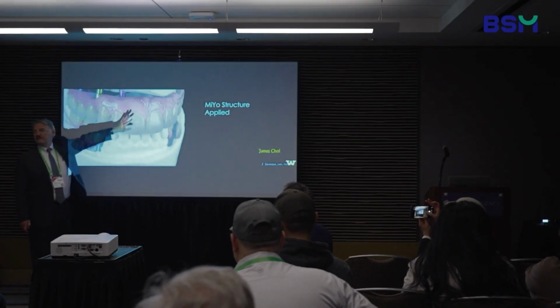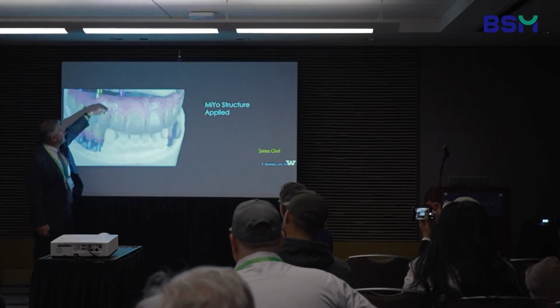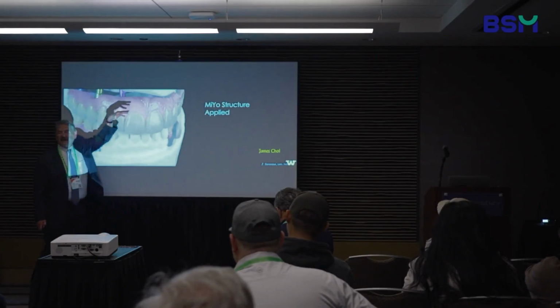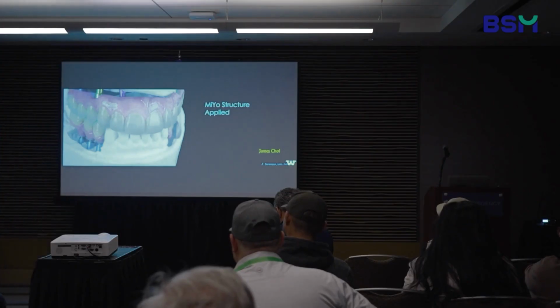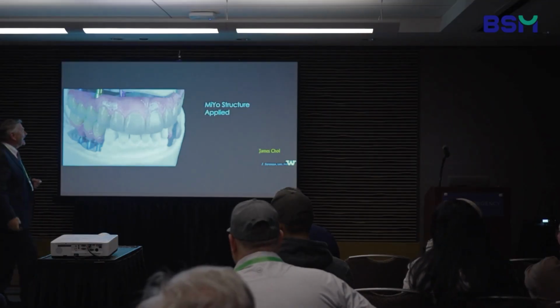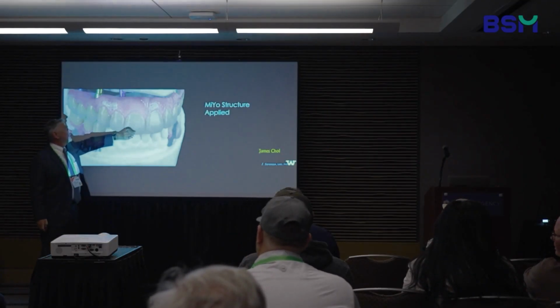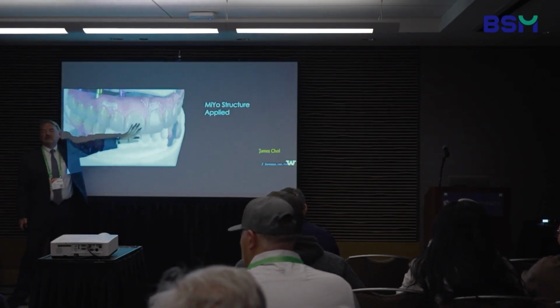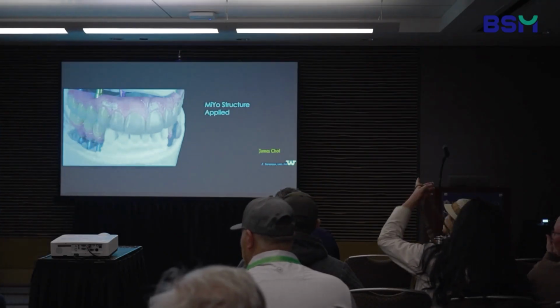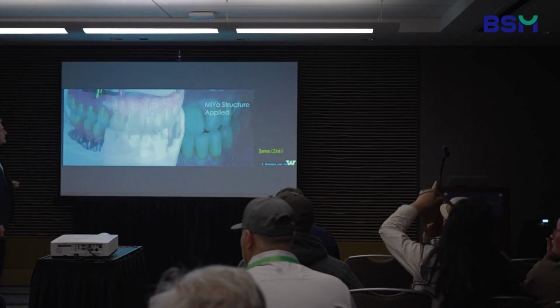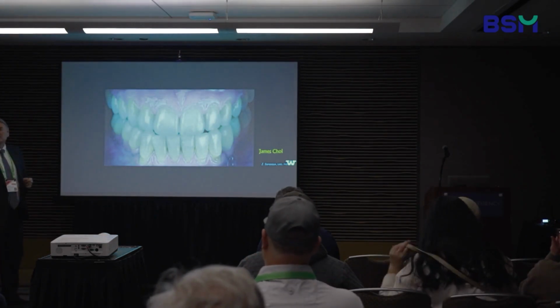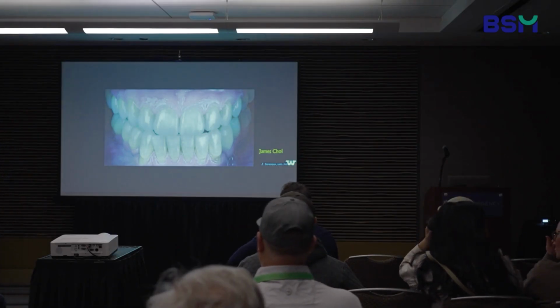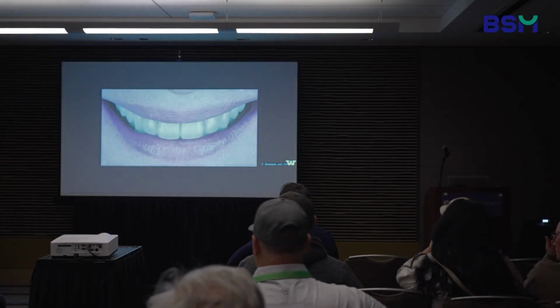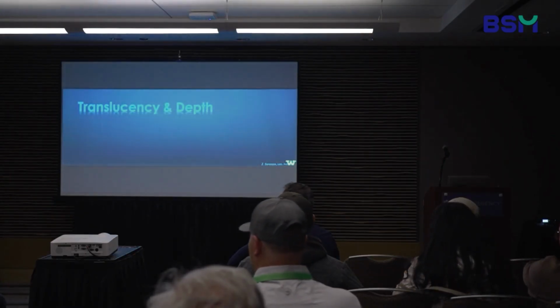This material is viscous enough that I can take a brush and make stippling in there, or I saw somebody doing a demonstration, and this technician was using an endodontic file and making little pits in there. It looked very natural. That's one of the problems our residents have: they don't apply the structure, so they have a very smooth surface, and the surface texture does not match the natural teeth. So just sensational results that you can get with this material, which has been very promising and helped us to achieve very nice results.